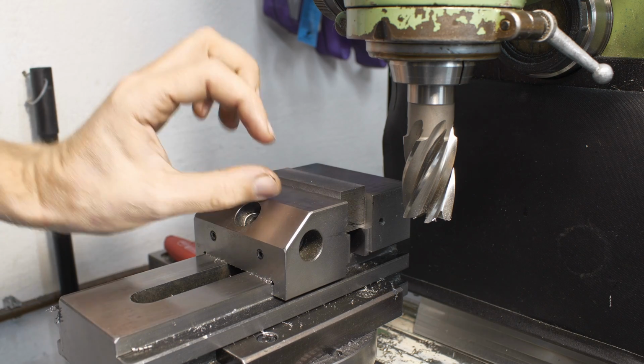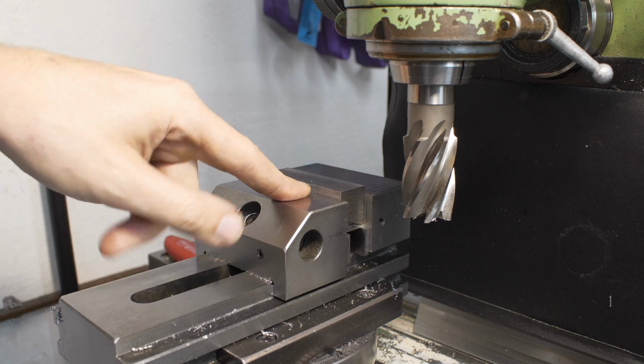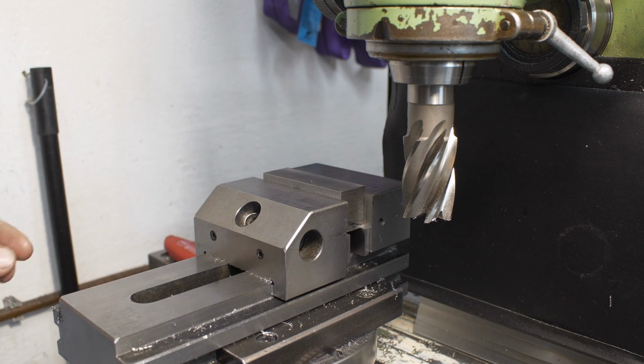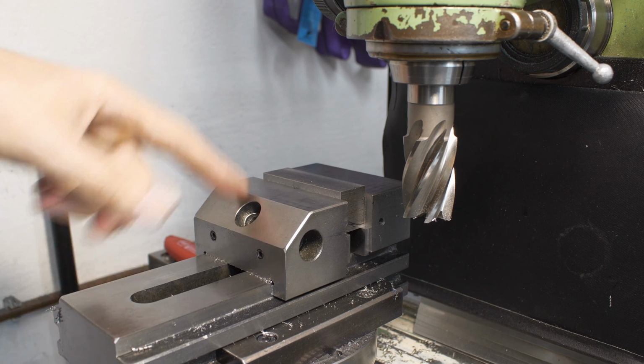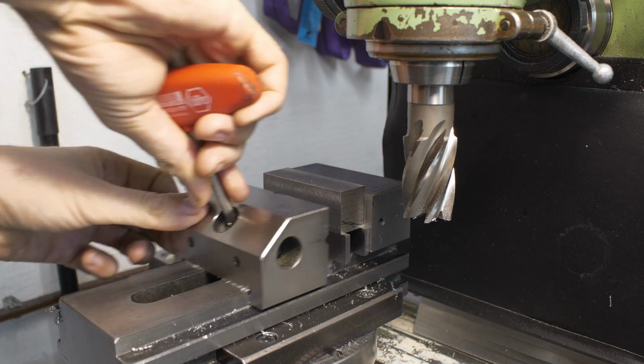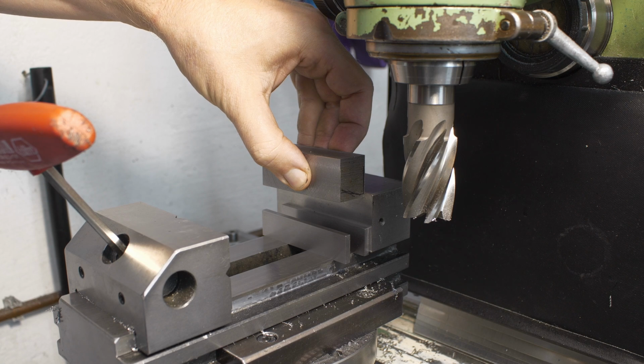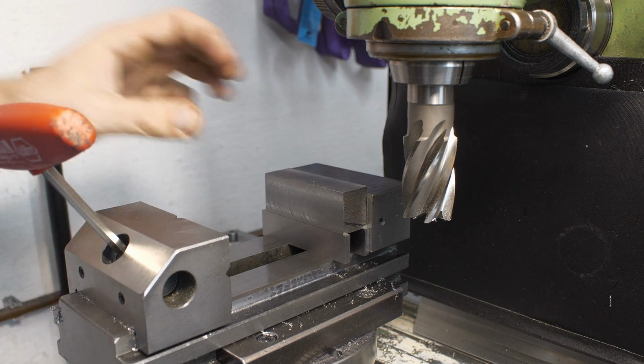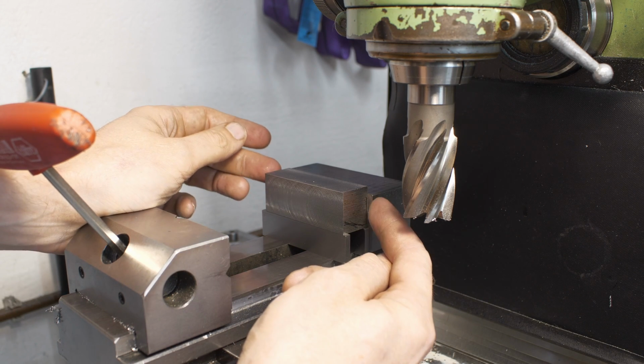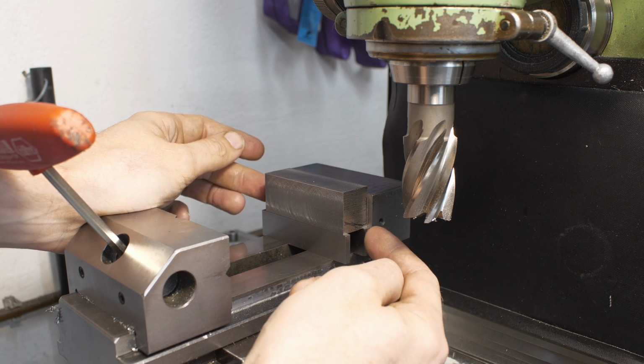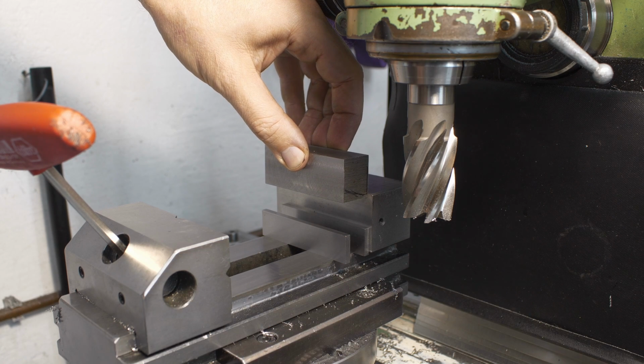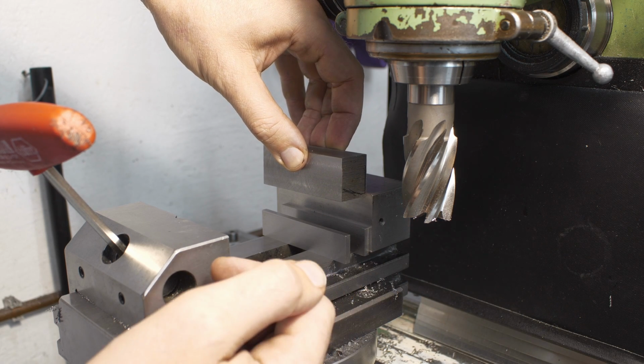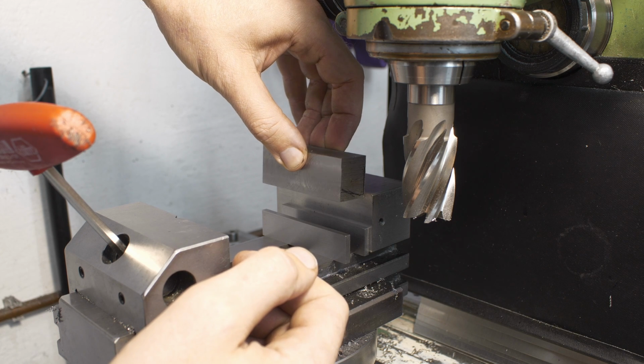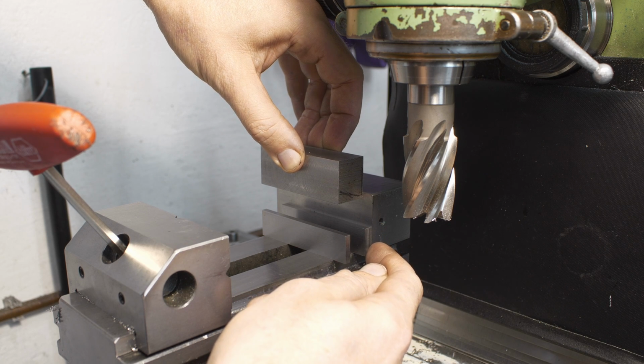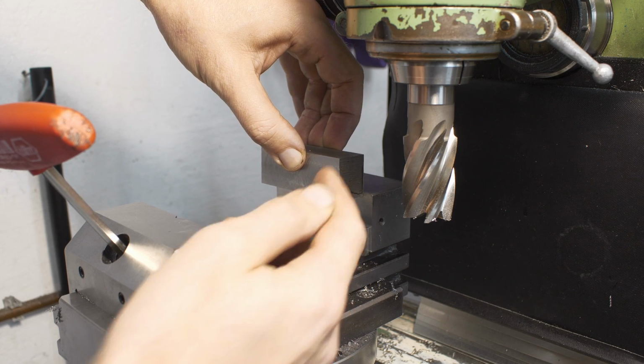And there are other techniques. You can also grab the stock on very little depth in the vise and just walk an end mill around. Then you have to fight cutter deflection, of course. But we do that on CNC machines a lot. Also, when you clamp parts in a vise, how deep you clamp it will change its behavior on what relationship you will achieve. If you clamp a part very deep against the fixed jaw, like here, the squareness is overriding the parallelism. If you go very far up on the jaws, like this, you are mostly going for parallelism, because the fixed jaw has very little engagement on the back wall of the part, and that way you're only going for parallelism. That way you can get both parallels to make full contact even without the part being that square.